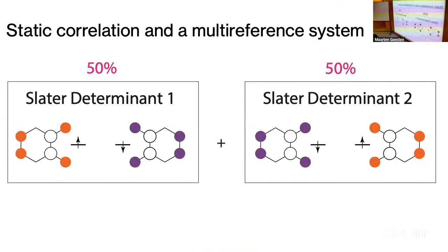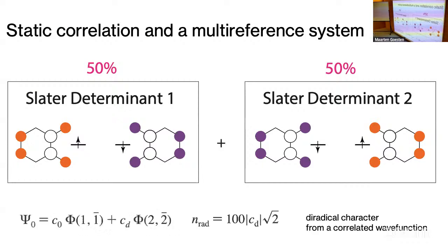But if you look at the real group theoretically correct wave function, you actually have to do wave function theory. In the simplest possible case of two interacting electrons, this wave function with spin up on the left-hand side and spin down on the right-hand side determines 50% of the total wave function. And here we have the reverse situation. In the real many-body wave function, these two are mixed, and then you obtain the group theoretically correct wave function. The only way to define it in a physically correct way, and this is all developed by Neese and Malrieu as well, is to do wave function theory, and then from the CI coefficients, you can describe a degree of diradical character.